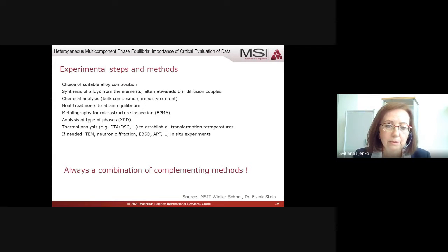Next, an important aspect is metallography for microstructure inspection, a method which is sometimes underestimated, but it is a very important method in understanding material behavior, and analysis of the crystal structure of the phases to identify them, and of course thermal analysis to establish all transformation temperatures. And if needed, there are more advanced methods like neutron diffraction, backscattered diffraction, and so on. Important on this slide is this sentence: ideally, if somebody investigates phase equilibria, he should apply a combination of complementing methods.